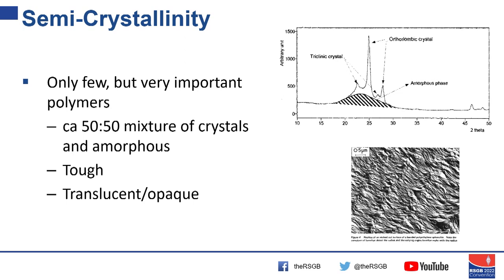And that gives you enormous toughness because the polymer chains pass through many, many crystals. They still roam around randomly through the structure, but passing through many, many, many crystals and locking them together. It means the materials tend to be translucent or opaque because the crystals scatter light. But it changes the properties dramatically.